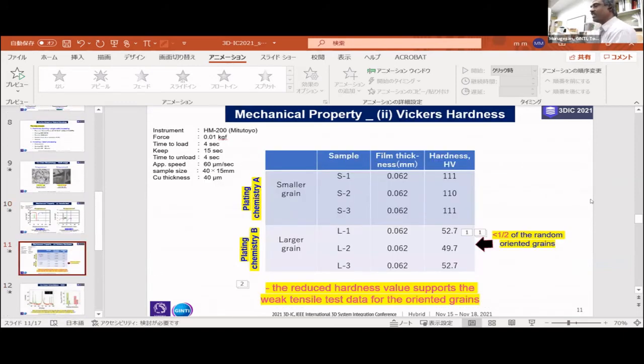And this is our hardness test. As I said for the tensile data, this hardness test also supports that our new chemistry copper film has very low hardness, nearly half of the conventional one. So this will help when you do your copper-copper direct bonding or hybrid bonding, to deform your copper and move it into other directions so that you get very intimate contact between top and bottom copper. So these properties are very important.